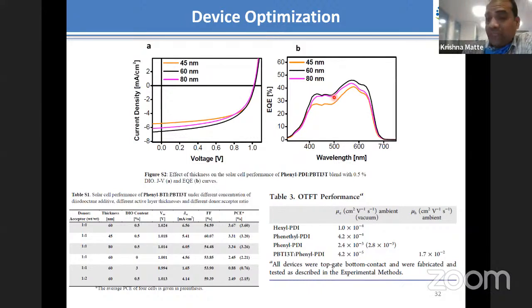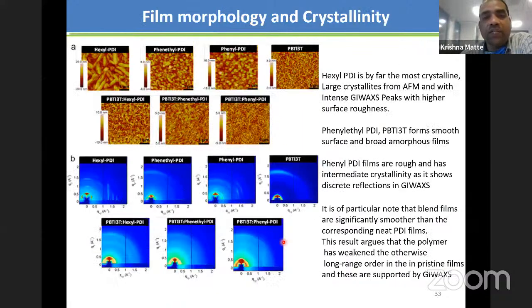because you have competing interests coming from the absorption and the charge transport. After that, we have to understand how these devices are working. We fabricated thin film transistors, and we found that the one which is working better has high electron mobility compared to the other two systems. So it helps you think about why your device is working for one given system compared to others.